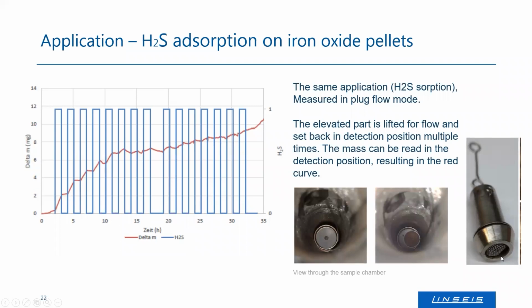There's a meshed bottom, and this meshed bottom is then more or less passed by the complete gas. This needs to be done in the following way. You put this complete basket at the bottom of the chamber. In the bottom of the chamber, you see in the left picture, there's a little hole where the gas comes out. So the magnet lowers the floating part completely. It stands on this little hole, and the gas passes the complete container.